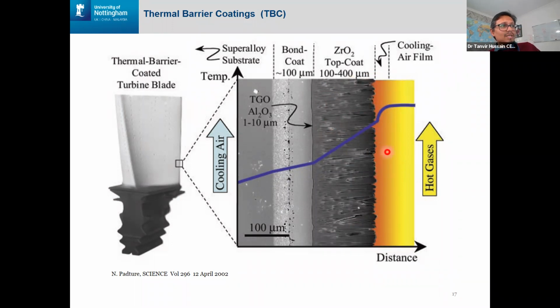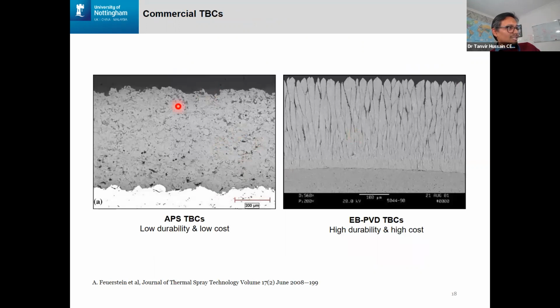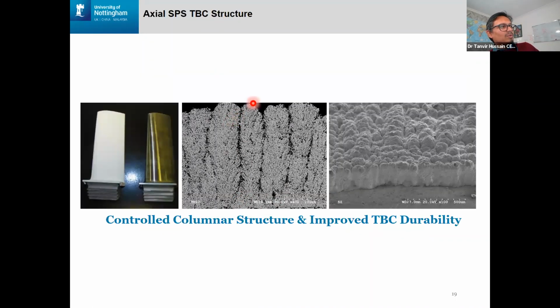But the problem is that EB-PVD systems are quite expensive. The sort of systems we have in this country, we're talking about around 13 million. And the process is quite slow because we're talking about layer by layer deposition of atoms. What suspension plasma is aiming at, so this is a conventional plasma spray coating. It has lower thermal conductivity because it has more porosity, or holes in it, compared to the state-of-the-art electron beam PVD. But from a strain tolerance point of view, this one is worse because it can't really expand or contract that easily. What the suspension plasma can do is produce this bird's feather-like structure, sometimes also called cauliflower-type structure, using a plasma at a fraction of the cost. So SPS systems installation-wise, we're probably talking about around 500,000, no more than that, versus 13 million.